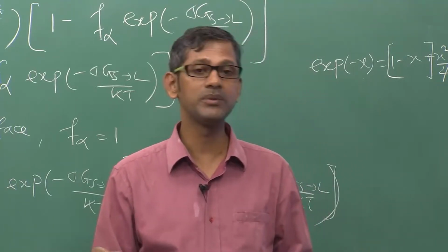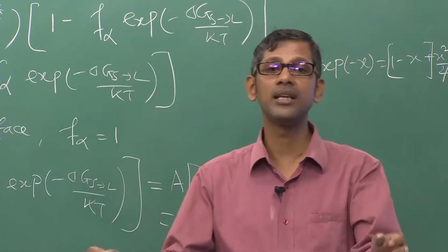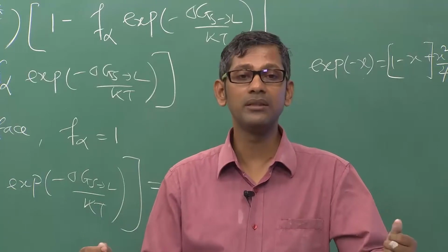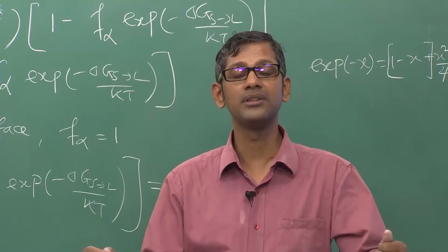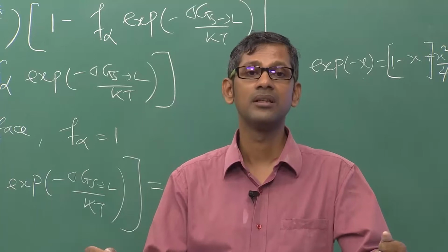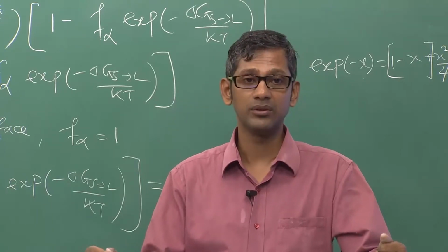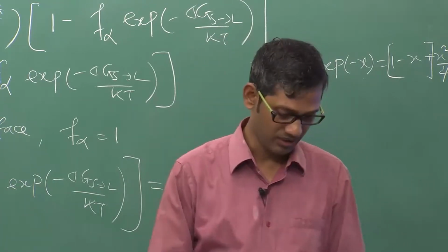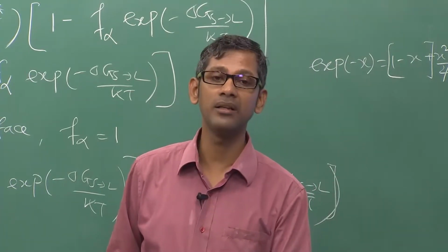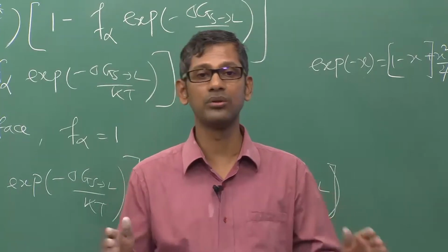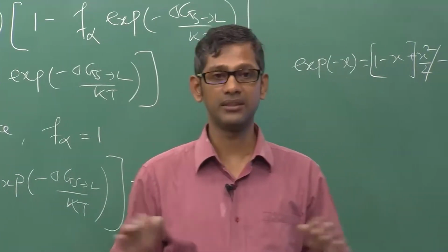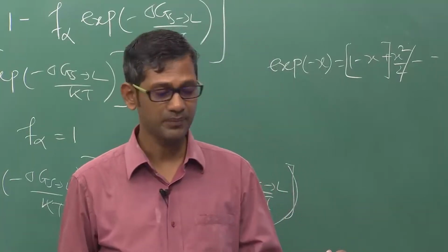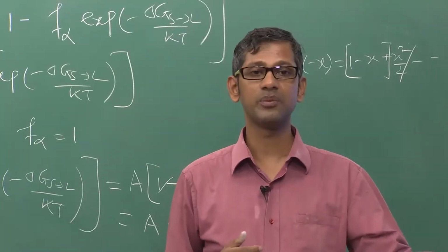And that's why in aluminum silicon alloys, the silicon gets multiple twins, and they have all kinds of features built in on these silicon fibers. So that's also another possibility. But we will not have time to discuss each of these cases in detail. These are there in the books. So we can have multiple situations of growth in the case of faceted interfaces, where you have small steps on these surfaces. We will keep on discussing all these aspects in the next lecture also.